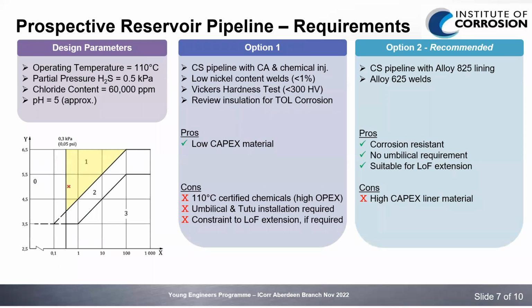So, material selection for the prospective sour field tieback. Before I go into the material selection, I'll describe the criteria the material had to facilitate. First of all, we have quite a high operating temperature, 110 degrees. We have partial pressure of H2S at about 0.5 kilopascals. We have 60,000 ppm chloride, and because of the CO2 and H2S concentration, we have a pH of just above 5. Combining the pH and the partial pressure of H2S, we end up in the sulfide stress cracking region 1 in line with ISO 15156. That's what's shown there on the bottom right-hand side.